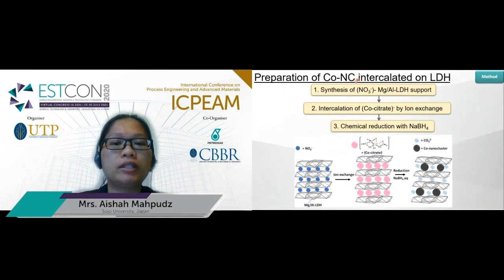For the preparation of cobalt nanocluster intercalated on LDH, the catalysts in this experiment are prepared using three steps. It starts with the synthesis of a nitrate type of magnesium aluminum LDH, where nitrate is the main interlayer anion. Following that is intercalation of cobalt citrate, whereby the nitrate anion is replaced with cobalt citrate in ion exchange. And thirdly is the chemical reduction with sodium borohydride, whereby the cobalt citrate in the interlayer is reduced with sodium borohydride aqueous solution to form cobalt nanocluster. So I will explain in detail each step.